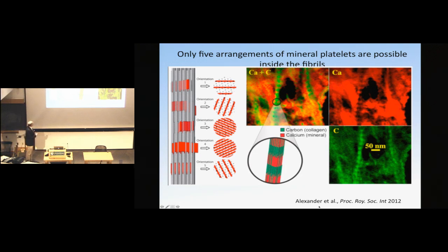However, the thickness of a sheath of mineral on the outside of these fibrils, added to either of those numbers, gives a number in the range of what an ashing experiment would give us. My question was, how did you estimate theoretically how big that sheath might be on the outside? That's just straightforward geometry. We know the volume fraction. We know the spacing between collagen fibrils. Collagen in bone is very similar to collagen in tendon. You chop a tendon and look at it down the axis, and you see it covers about 80% of the area.